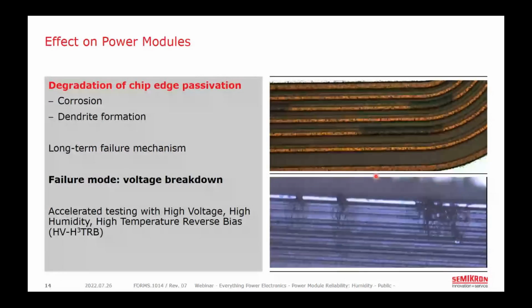Once those water molecules have accumulated on the surface of the chip, whether through electrical or thermal means, the water can cause corrosion. This is of concern at the edges of the chip, where there is a combination of passivation and field plates that have been designed to lower the critical electric field strength and prevent voltage breakdown across the edge of the chip here. This moisture can corrode these field plates or even cause dendrites to grow that can short out the plates.